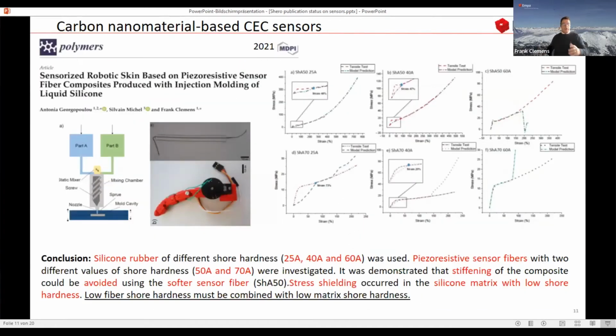While Cambridge was looking at that, we still tried to investigate and analyze again, for the other people who are working with us in this field, how the self-healing matrix must look, so that it is comparable in a good way with our sensor, or with the new sensors which have also been developed from self-healing materials. You can see here again, we did a more systematic study where we worked with two different shore hardnesses of the fiber and three different shore hardnesses of the matrix.